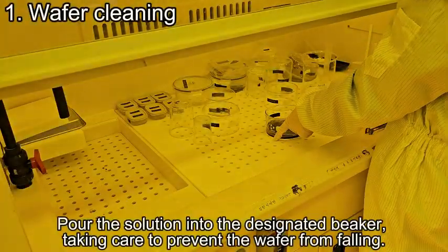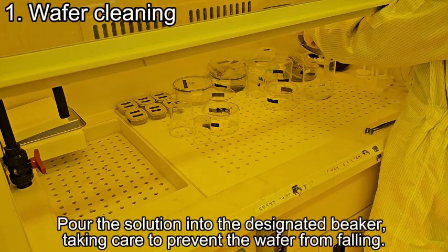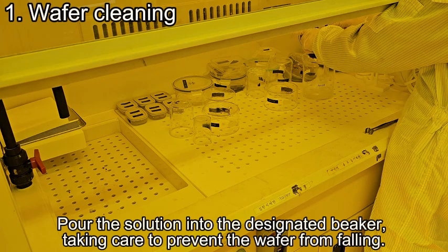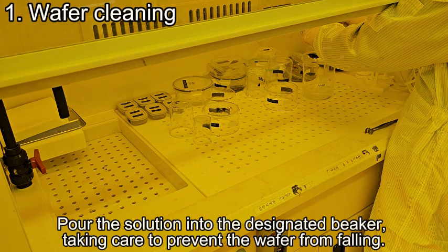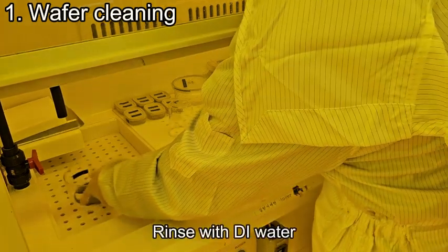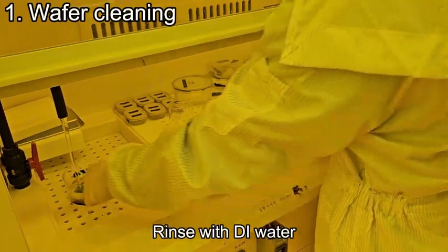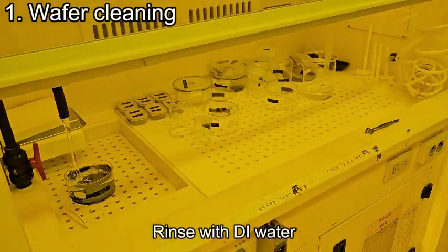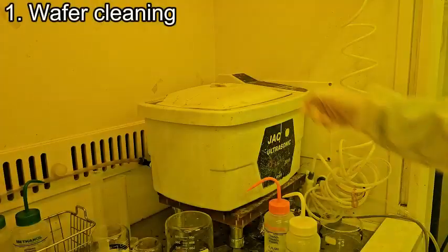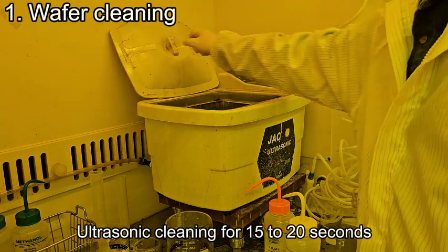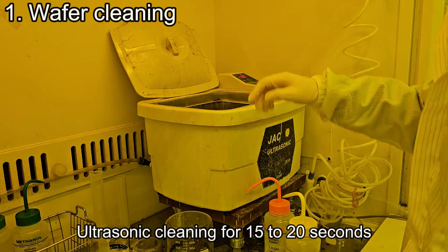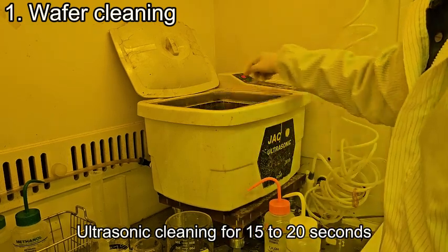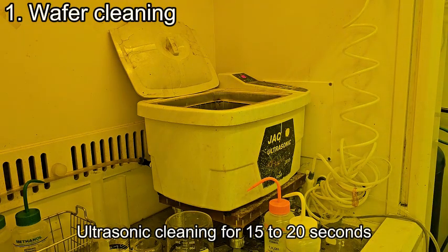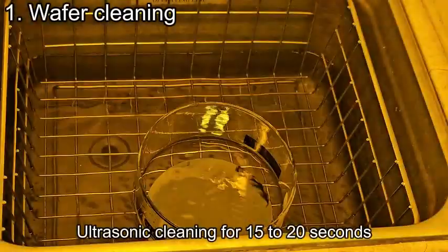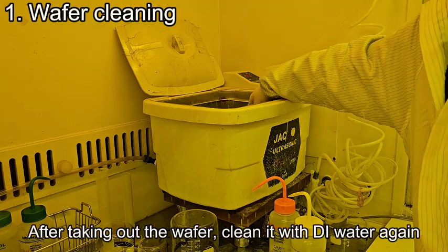Pour the solution into the designated beaker, taking care to prevent the wafer from falling. Rinse with deionized water. Ultrasonic cleaning for 15 to 20 seconds. After taking out the wafer, clean it with deionized water again.